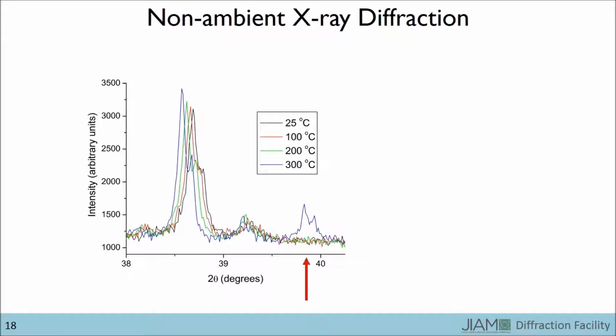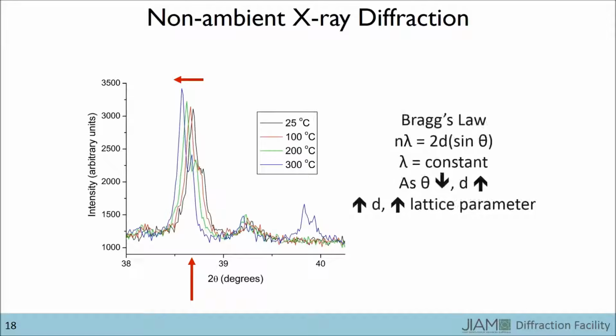The first item to note is that we see a new peak appear just below 40 degrees 2 theta in the pattern collected at 300 degrees Celsius. Using the full diffraction pattern, the user was able to determine the identity of this phase. More experiments could be carried out to better determine at which temperature it first appears. Looking at the peaks around 38.7 degrees 2 theta, we can see that as the temperature increases, the position of the peak shifts to lower 2 theta, indicating an expansion of the lattice parameters.